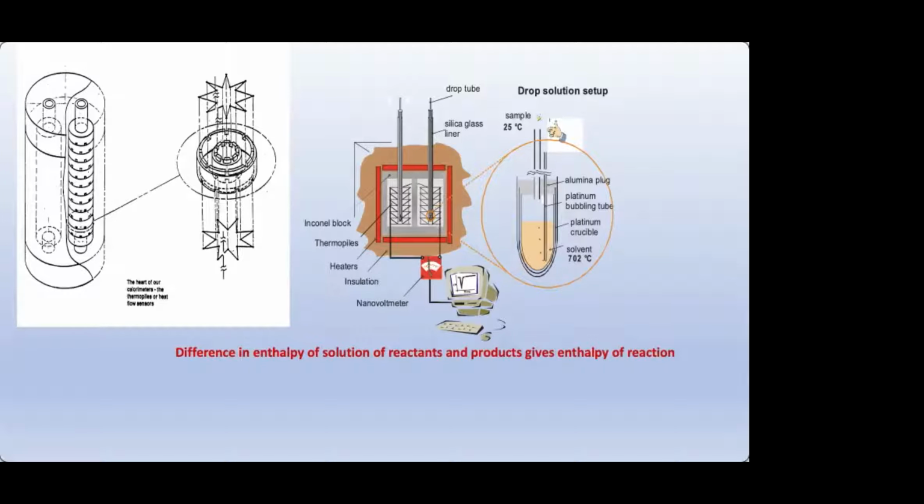We often stir the melt and control the atmosphere by gas bubbling. And the accuracy that we typically get is on the order of between 0.5% and a couple of percent in the heats of solution, and therefore a few tenths to a couple kilojoules per mole in the heats of reaction or heats of formation. Choosing the proper molecular weight for comparing materials is something that one has to pay attention to.